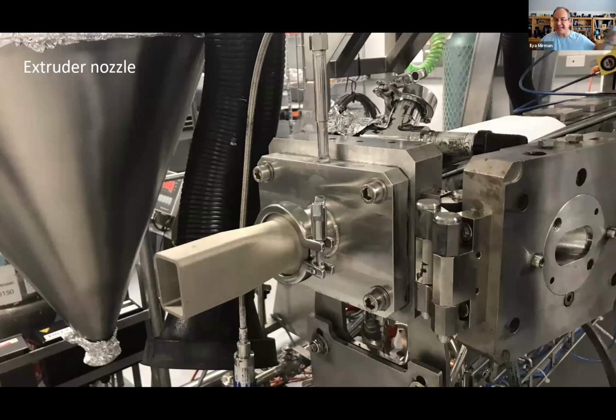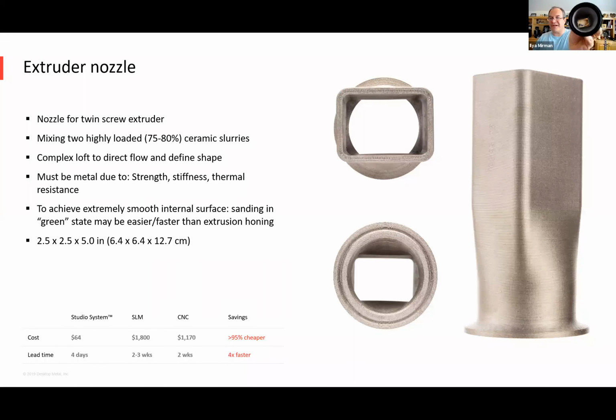Do extrusion dies. Here's an example. This is a twin screw extruder that's mixing and pushing a dense ceramic slurry through this extruder. I'm going to take this off. So here's the interface, and here is the part in question. You see there's a gasket on this end. So you basically start with a circular profile, and you end with a rectangle. It's a rectangle because the final part is like you're extruding pasta, except you're extruding ceramic mixture. The goal here is to create a rectangular shape. You need to start from a circle because that's the standard interface to the extruder.